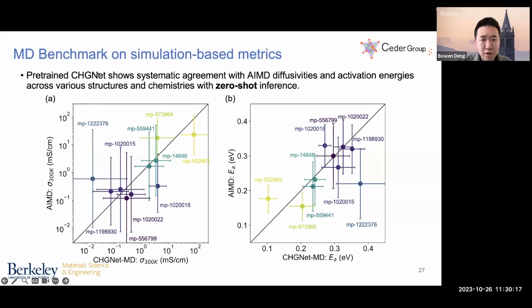So we applied the pre-trained CHGNet to simulate molecular dynamics at elevated temperature, in exactly the same process as mentioned in that previous paper, and we extrapolated to room temperature and observed the room temperature conductivities and also the activation energies. What we observed is that CHGNet has perfect agreement with the AIMD simulated diffusivities, with all of the data points within the AIMD error bars, and with only zero-shot inference. So CHGNet has learned nothing on these trajectories, but is able to predict which conductors are better than the others, as discovered by DFT.